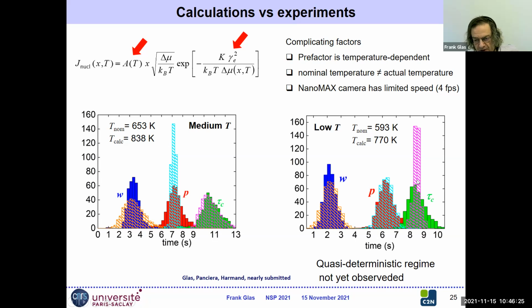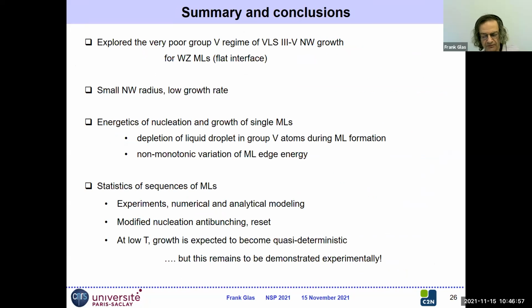And it's very important because if you manage to get into this very narrow tau c regime, then you have quasi-deterministic growth. You can say that even with standard growth equipment, I know the growth conditions, ideally, then I grow for a certain time, and I'm sure that in this time I will grow exactly this number of monolayers. So this quasi-deterministic regime would be very interesting for nanowires, for heterogeneous structures, and so on. But at the moment, it is fair to say that we have not quite observed it.